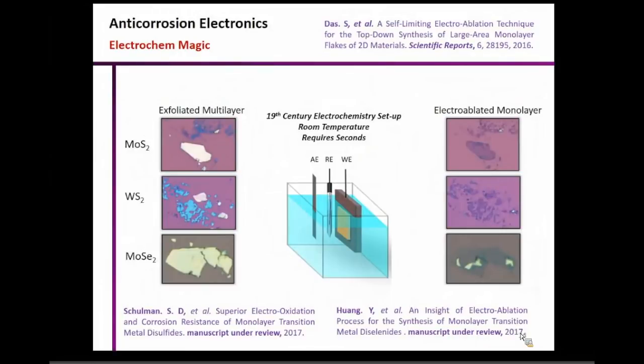The other thing, which came out of some accidental discovery when I was working at the Oak Ridge National Lab, is that these 2D materials could also act as anti-corrosive electronics. For example, if you want to monitor chemical processes, you might want to put sensors inside chemicals, and you don't want those devices to degrade with those chemicals, right? So you need something that will survive toxic, oxidizing, or corrosive environments. What we found is that when you take these multilayer 2D materials and put them on a titanium nitride substrate, and then do some electrochemistry where you apply a very large positive potential, generating a lot of oxidative species like hydrogen peroxide, the multilayer flakes are actually converted to monolayer.